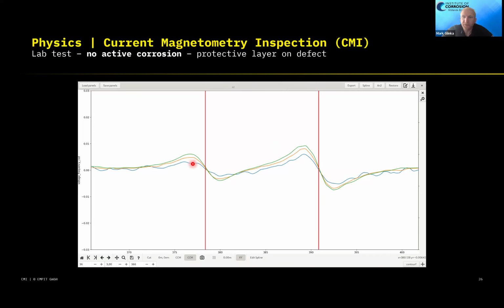So what do we need to do electrochemically to actually have this behavior? We need to build in a capacity in the system, and the capacity goes with the frequency, and our capacity is our soil to steel interface. So that's our protective layer. So actually we can see, dependent on the capacity or on the spread resistance and the difference of the spread resistance for each frequency, if we do have this passivation layer or not. So over here, let's say it's a calcareous deposit, it will obviously cause an attenuation in the lower frequencies. We can see this directly.